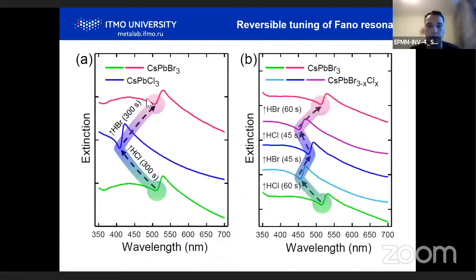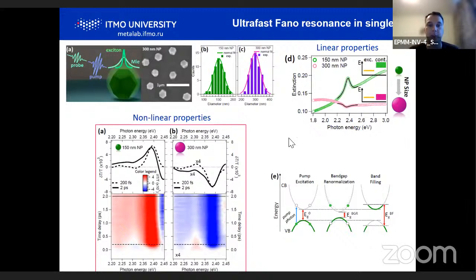And we can do it due to complete doping or partial doping, and we can apply many cycles in this chemical reaction to provide multi-cycle tuning of our nanoparticles, nanoantennas. So also, Fano resonance can be tuned in an ultrafast manner. As you see in this application, we demonstrated ultrafast tuning in less than 1 picosecond at some wavelengths. We can modify the properties of these Fano resonances quite dramatically.